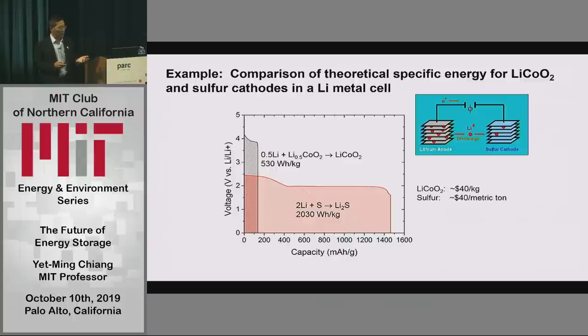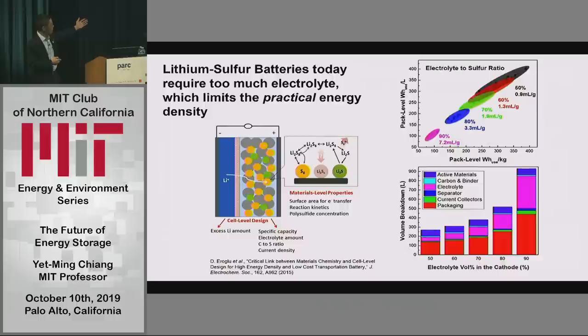Right. So it turns out that we've been trying for about 30 or 40 years to advance lithium sulfur batteries to where we could take advantage of something like this. Looks great, right? Why wouldn't you do this? Right. And so just to point out one really practical issue, it turns out that in order to make that lithium sulfur battery work, we use a liquid electrolyte, and every time we charge it, part of that liquid electrolyte dries out and becomes a solid. And we cycle it until it's dry, and when it's dry, it dies. And unfortunately, it takes a very small number of cycles for that to take place.